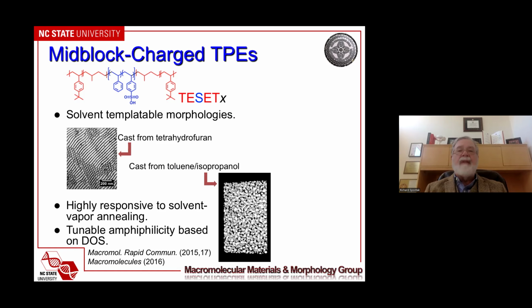What's unique about this material from a polymer physics standpoint is that you can change the morphology of these self-assembling materials simply by changing the solvent. So we can either have, as you see over here, coexisting alternating lamellae and hexagonally packed cylinders, or we can have dispersed ionic domains down here. Over here, the ionic domains appear dark because of selective staining. Here, the contrast is reversed, so you can better see those domains. So that's one thing. They're solvent templatable, but these materials cannot be subjected to thermal annealing. So instead, we use solvent vapor annealing.